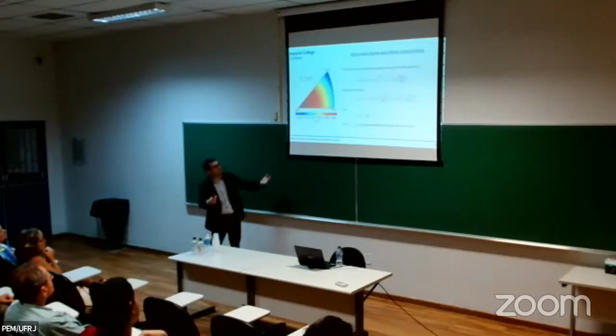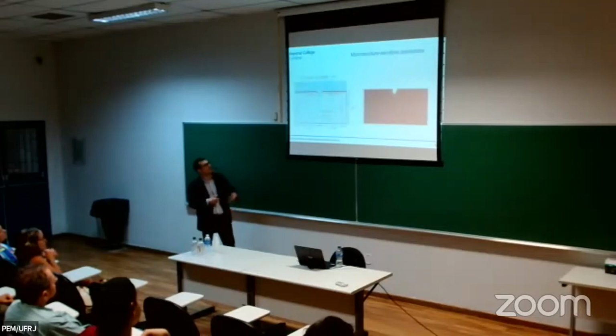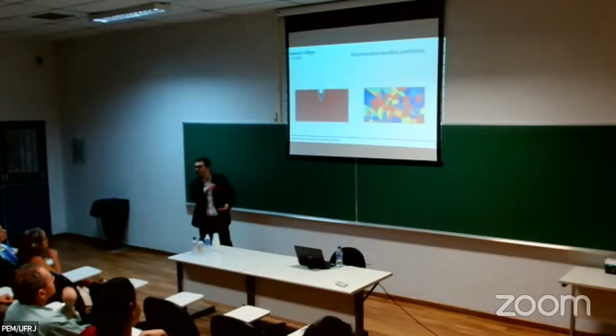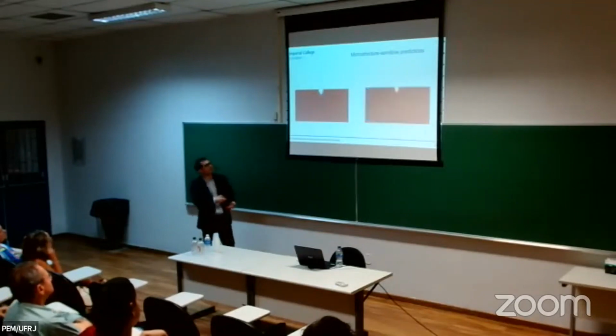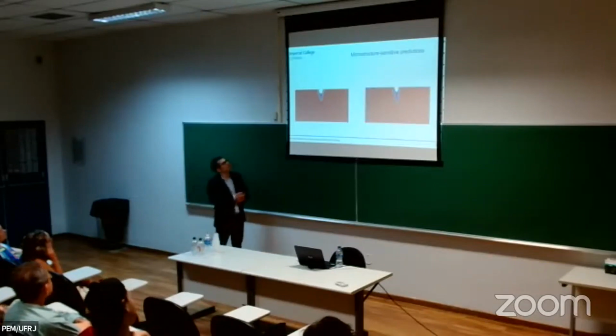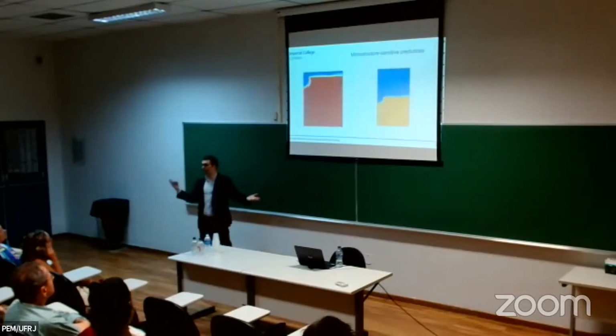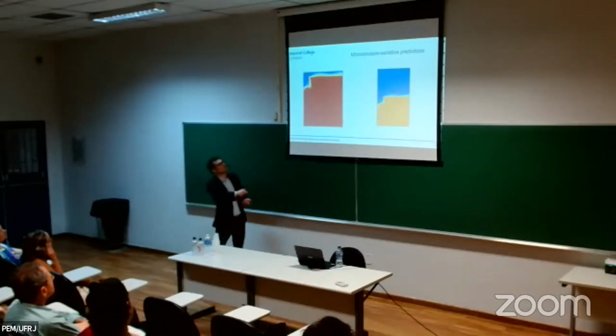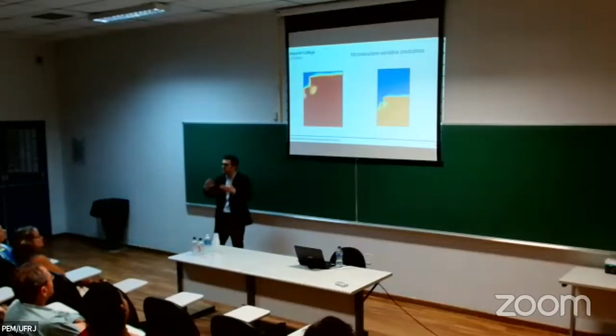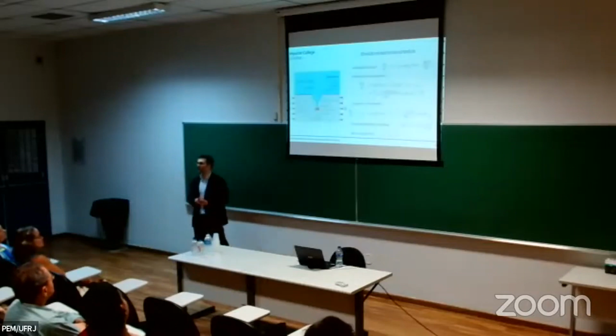So we can extend the model and define a grain orientation dependent corrosion potential, and we can then capture the effect of the microstructure. So you can see here, this is a microstructure insensitive calculation, but we can have any microstructure that we wish, and we can see what is the role of the microstructure in changing the corrosion process. And we can also do more complicated things. For example, you can have secondary phases, and the corrosion will not deal with those insoluble phases. So you can have very complicated microstructures in your model, and you can also capture the role of the chemistry.